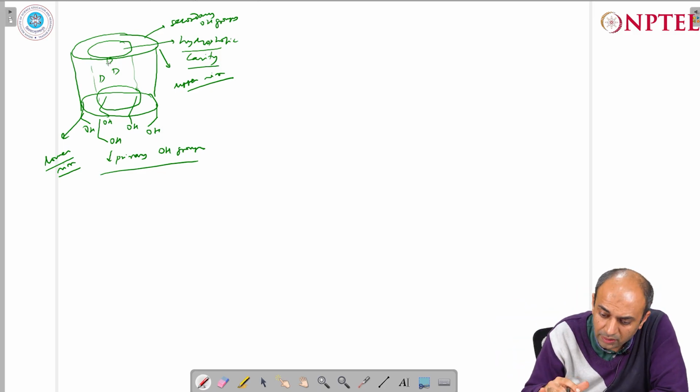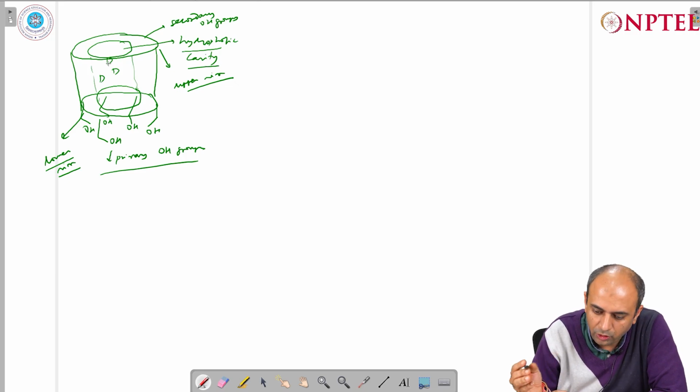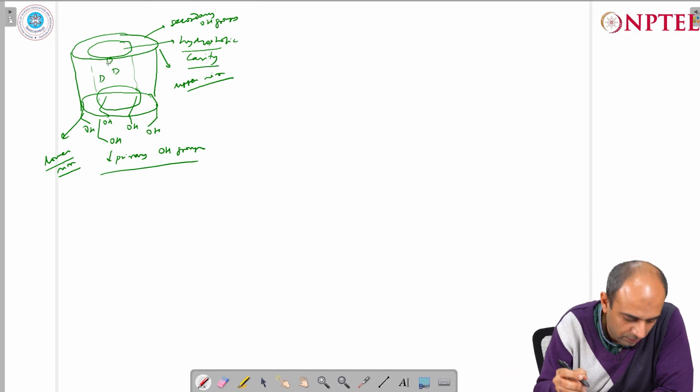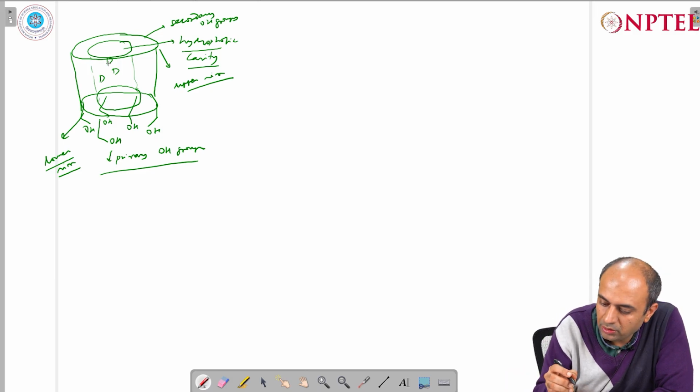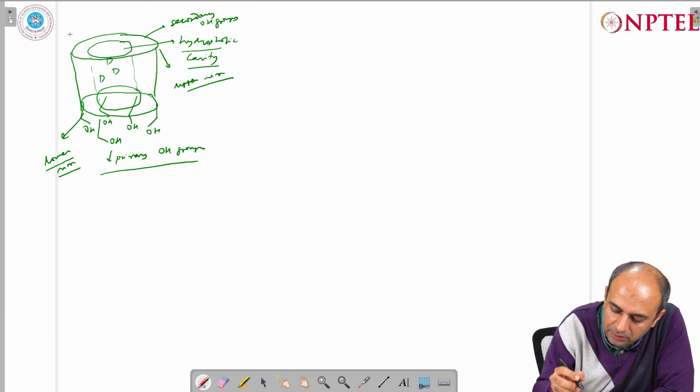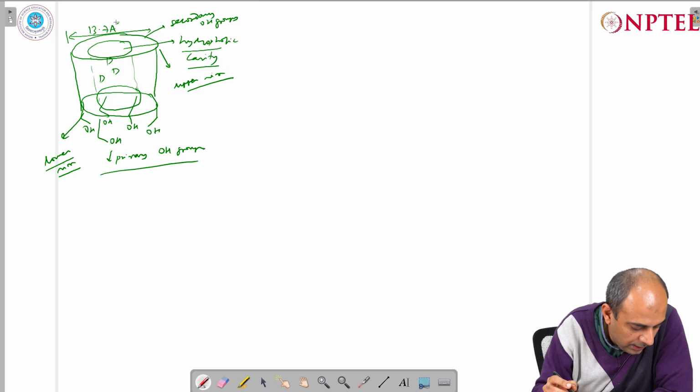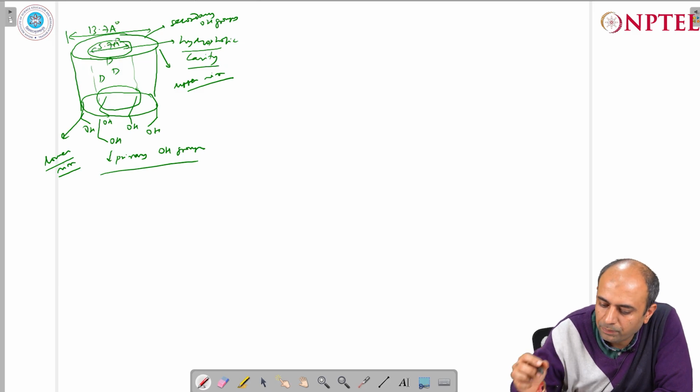So this is the shape representation of a cyclodextrin, and what has been observed is the following. We can now specify some of the most important geometrical dimensions of this particular cyclodextrin, which we call the anatomy. This particular separation is 13.7 angstrom, and then the inner one is 5.7 angstrom.